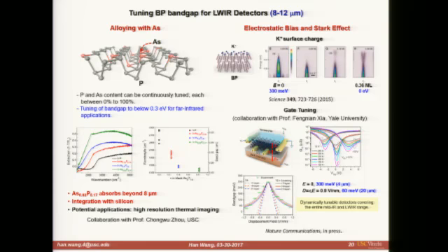So in order for black phosphorus to detect photons at longer wavelengths, at lower energy, we have to reduce its band gap. 0.3 eV corresponds to about 4 microns, which is too large of a band gap for this range. So we have two different approaches we're working on.